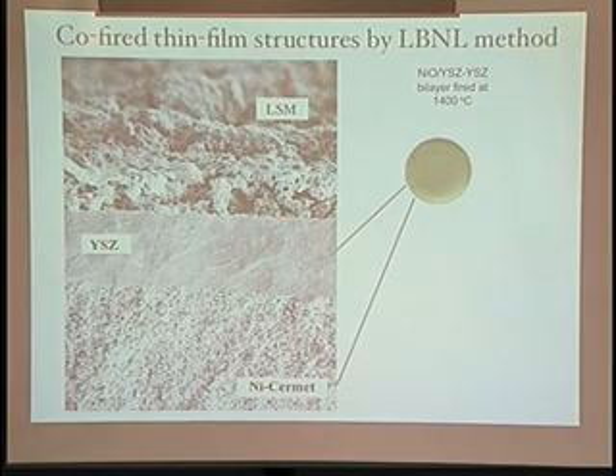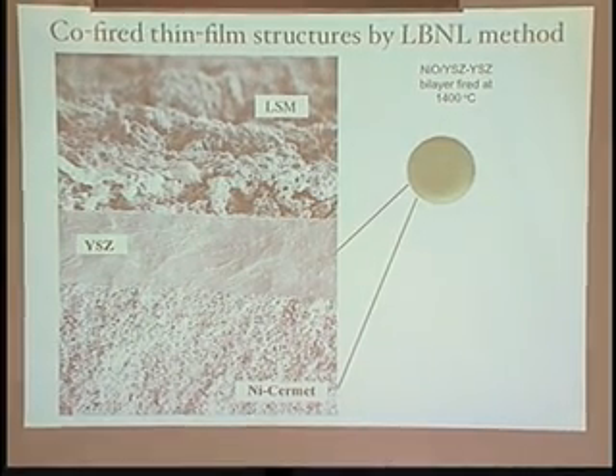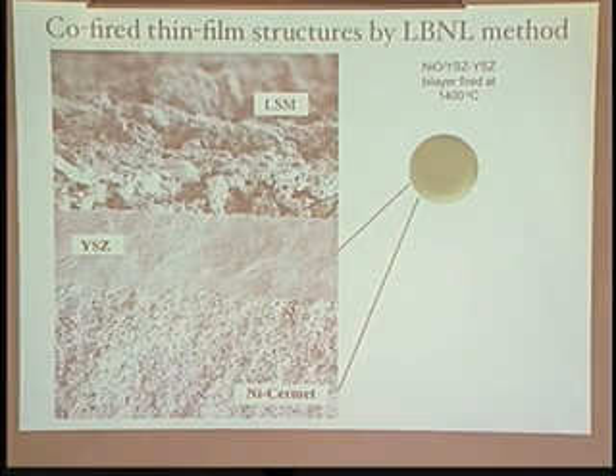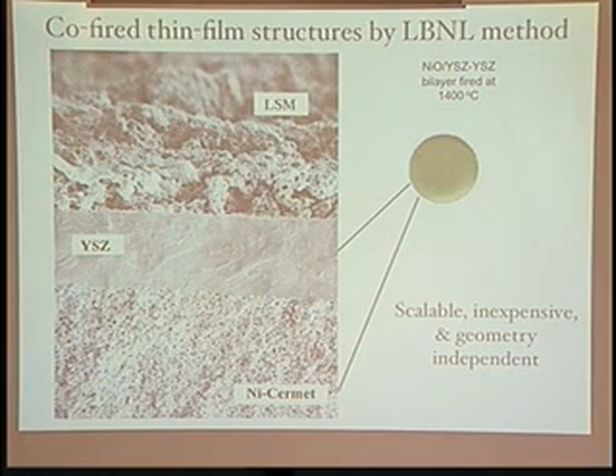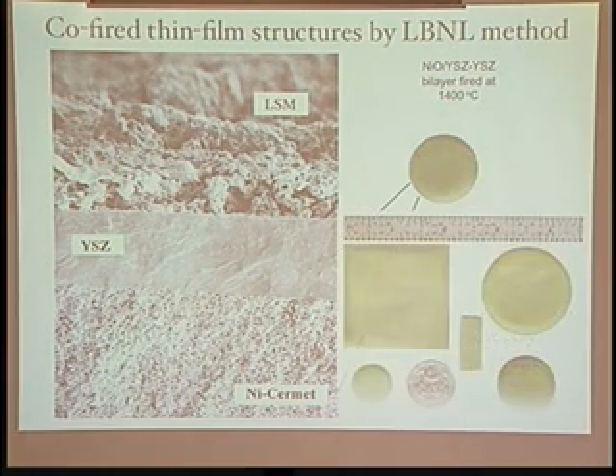If we look in cross-section, this is actually a scanning electron micrograph, this is the zirconia film, and that is about 15 microns thick. And you can see it's perfectly dense, and it's sitting on top of a porous electrode. This is where the hydrogen comes in. And this is the air electrode. And this technique is scalable, it's inexpensive, and it's geometry independent. So you can see just at LBL alone, we can make squares, circles, plates, in fact, tubes.